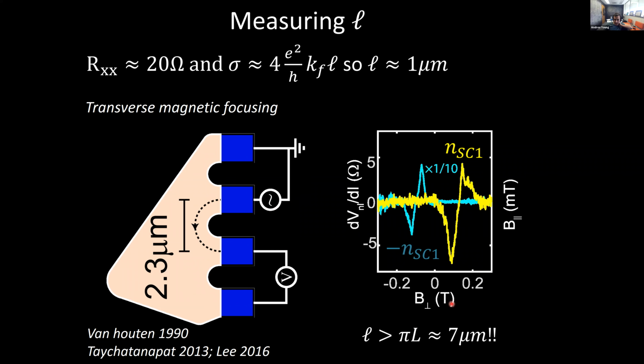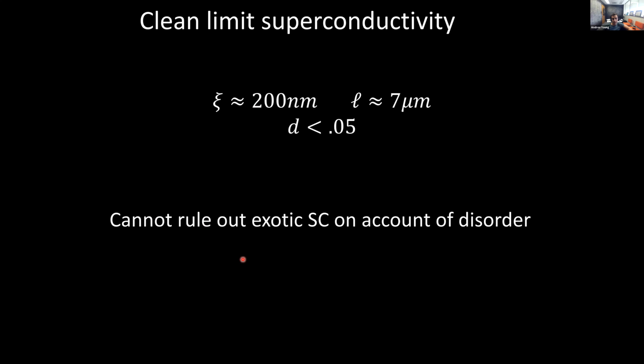And this is a resonant effect as a function of magnetic field, and actually you can see the signatures of this effect right around the densities where the superconductivity occurs. And if you think about the device geometry of 2.3 micron or so spacing between these, this basically implies a mean free path on the order of 5 to 10 microns. So really quite large. This is basically a signature of ballistic electron transport with no scattering off of disorder inside this system. So we certainly are strongly in the clean limit, in that the mean free path is much longer than the coherence length, and so at least on those grounds we can't immediately rule out an exotic form of superconductivity.